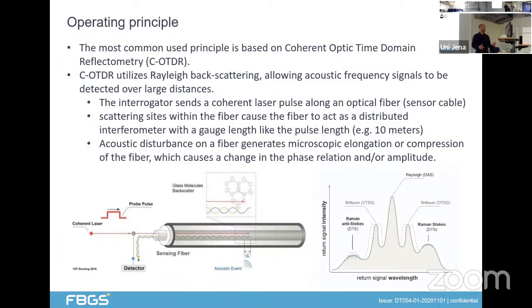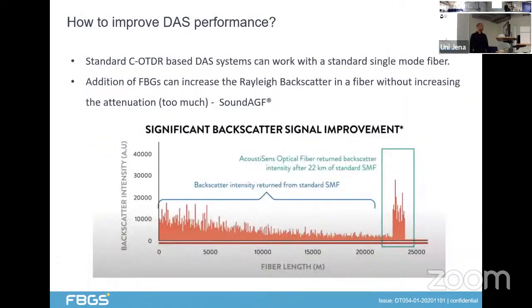The acoustic disturbance along the length causes small elongations and compressions, and these are usually picked up. When we look now at such a signal, on the bottom there's a graph over the fiber length of a standard single mode fiber, which is typically used for that. So there are normally no gratings inside. That's standard fiber of 22 kilometers. One can see that the signal drops, and at the end we have really low signal and higher noise.